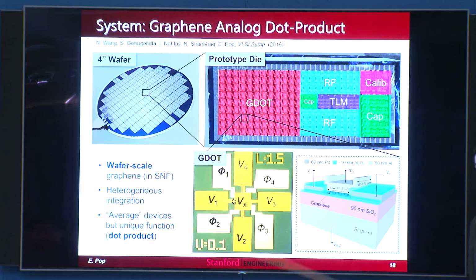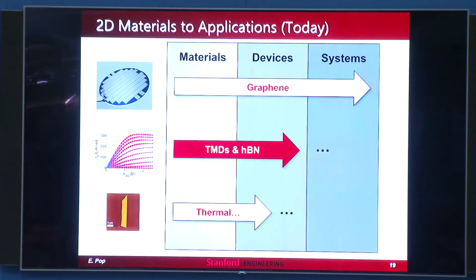And also the fact that we are able to focus on a fairly unique function where graphene actually shines compared to silicon because of its higher mobility. So if you do the same thing in silicon, this will actually be slower. And you'll still get the right answer, but it'll be slower. And so graphene is really better here because of the higher mobility. OK. So that was the part on graphene, just selecting a few things from the graphene work.